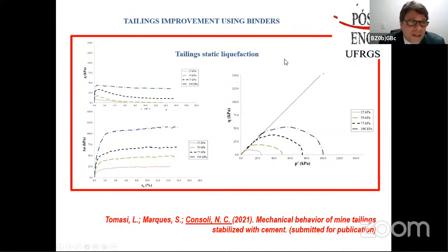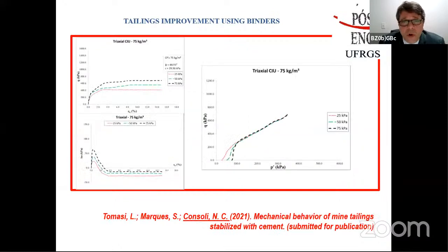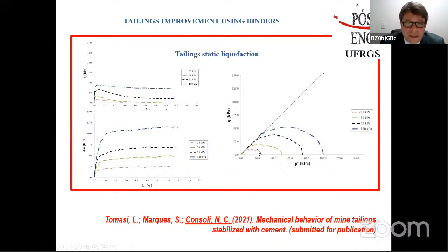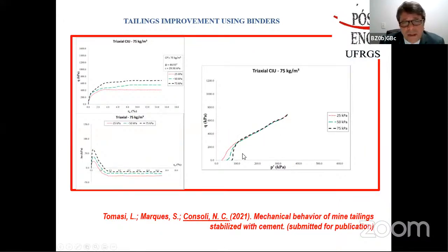In order to try to avoid that and solve the problem, one of the things that we are studying at this moment is adding small amounts of cement to these tailings in the place where they are. In this case, adding amounts of, for example, 75 kilos per cubic meter, you might have a completely different situation from the previous one, in which without cement you had a possibility of liquefaction. When you insert small amounts of cement, you have a completely different behavior, as we can see here, even with the production of negative pore pressures in this undrained triaxial testing. This is a paper that is being written and was submitted for publication, not accepted yet.